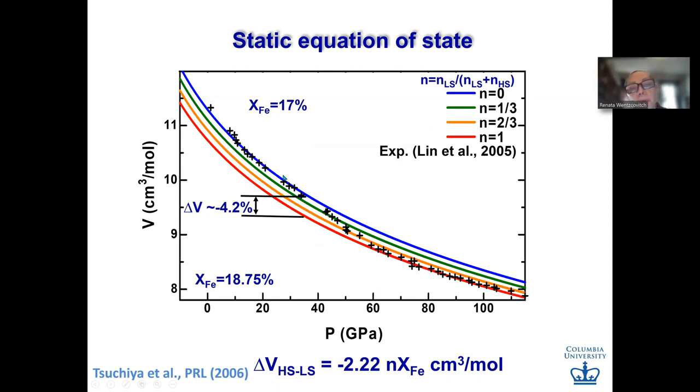And when you superpose the experimental data, you see that there is a large spin crossover here. The transition pressure starts actually at 40-45 GPa and doesn't end until 65 GPa. It's a broad transition pressure range. The way I interpreted the experimental compression curve is that irons are not interacting with each other, because I don't see a change in transition pressure.